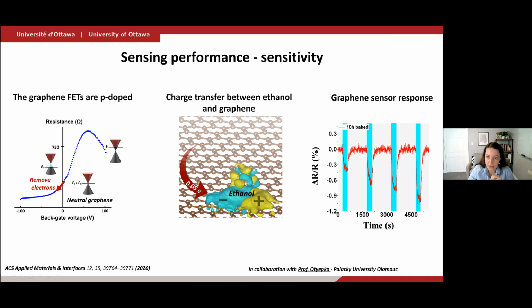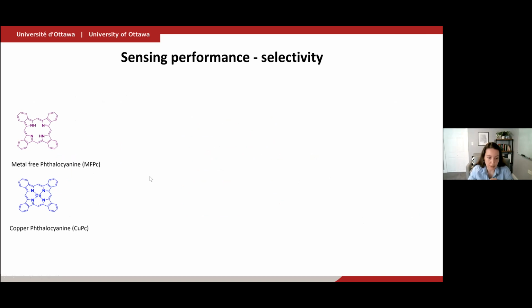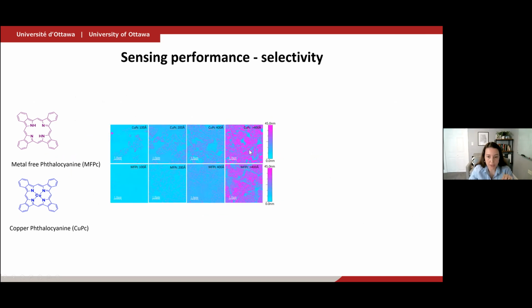But of course, sensitivity is not enough to make real sensors. You also need them to be selective. And so towards that goal, this is work that is now published. It's also being written. We've been using functionalization of the surface. So we've been using metal-free phthalocyanines and copper phthalocyanines. These are prepared in my colleague Benoit Lessard's group. We place them on the graphene surface.